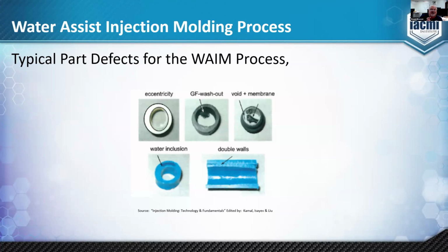The part defects that you can see in the water assist is the concentricity of the hollowed out sections. It is usually very good with water assist, much better than gas assist. If you're using a glass fiber system, you can push fiber out of the material and into the water channel. You can also create double walls with voids or membranes across the water channel, or you can actually have water inclusions into the wall of the polymer outside of the hollow section.